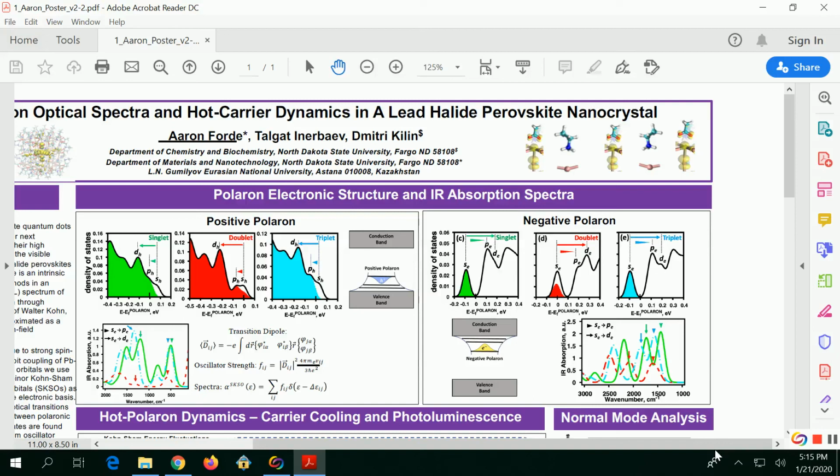So you were able to heat them and do several steps of molecular dynamics. Mm-hmm. But for any of the models that have a P occupation, those ones just have trouble heating. Probably, as Levi comments, because of the crossing of quantum energies, which means changing of the identity of the orbitals.